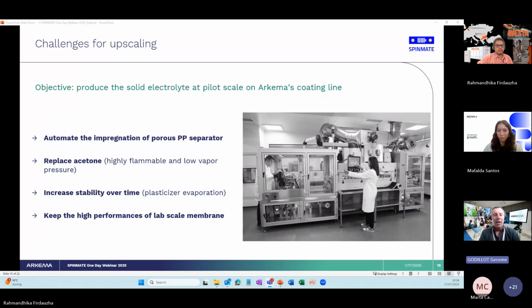We also found out that we had some evolution of the lab scale membrane. Properties are good, but we have some plasticizer evaporation. The stability over time is not that good. We are losing some properties with time. So this is something to be solved if possible with the upscaling. And last but not least, we have to produce a membrane at large scale while keeping the good performances of the lab scale membrane, which is always the main objective of the upscaling.